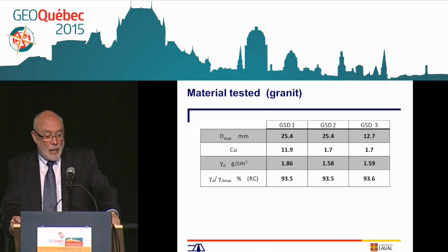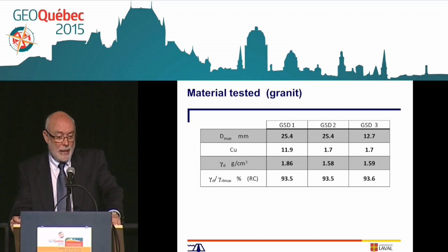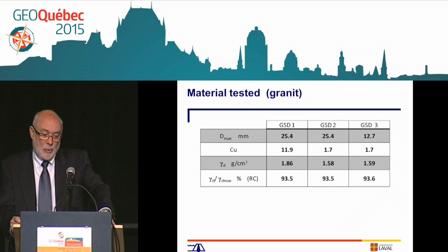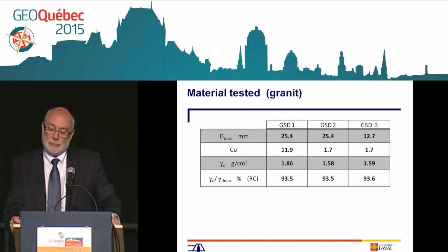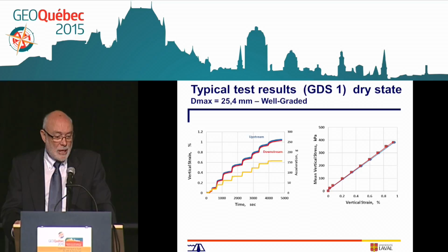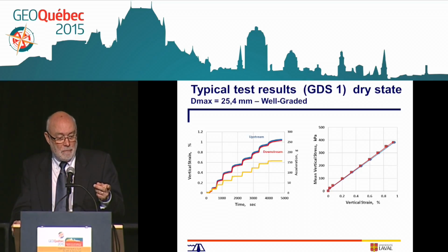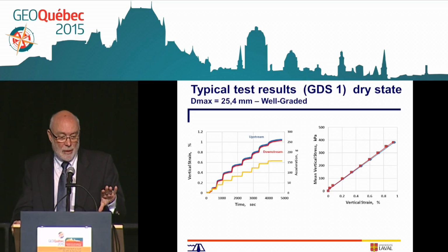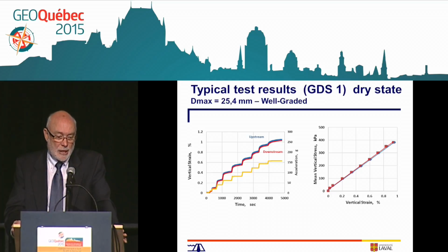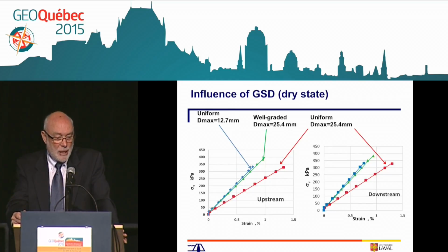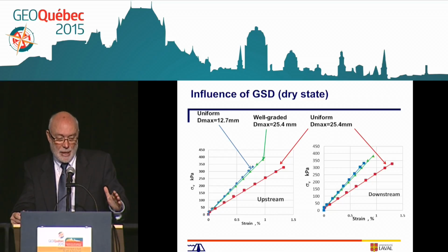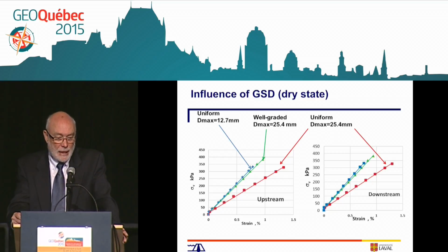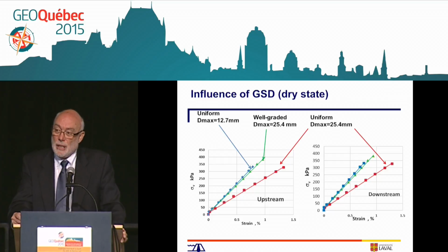One is well graded with a CU value of 12. The other one is a uniform CU of 1.7. And the third one is smaller grains. Those are typical results during construction. And as you see, the upstream and the downstream show the same behavior. It's still fairly linear stress strain curves for the well-graded material. And this is for older material. There is some effect. And we see that the uniform distribution with the maximum grain size is the less rigid in response.